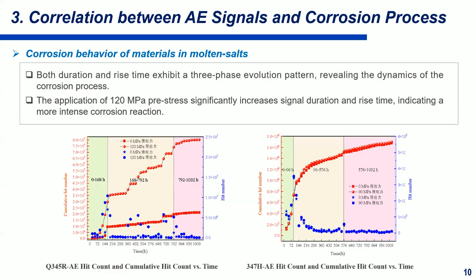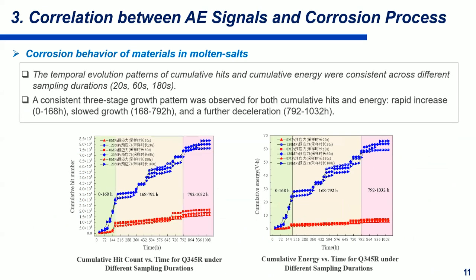Both duration and rise time exhibit three-phase evolution patterns, revealing the dynamics of the corrosion process. The application of 120 megapascal pre-stress significantly increased signal duration and rise time, indicating a more intense corrosion reaction.